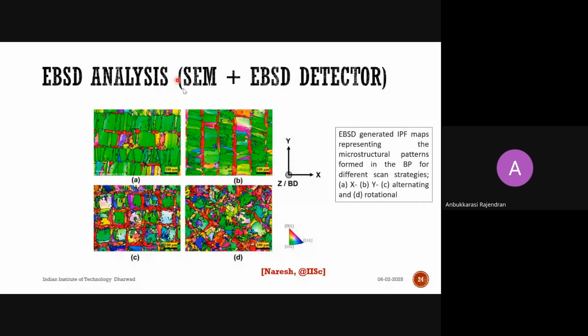Yes, along with the SEM, addition of an EBSD tool can give additional information about the grain size distribution, even the presence of stress, grain orientation, many things we can analyze. So this is one of the 3D printed parts, looked at for the grain size distribution by using the EBSD technique. These are the similar or corresponding images to what I showed for the optical analysis. One is printing along the x-axis, another is printing along the y-axis. One more is alternate, and the fourth one is the rotation way. So all the different ways of printing, how they affect the internal grains, right?